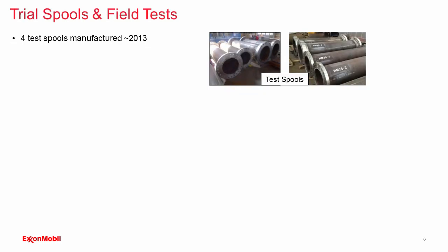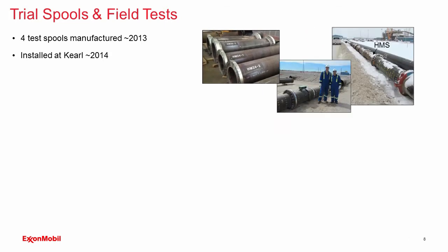We made some trial spools, some trial pipes. These pipes, 4 test spools, were manufactured in 2013. They were about 3 meters long, and they were 24 inches in diameter and 30 inches in diameter. That's 0.6 meter and 0.75 meter in diameter, and they were installed at the Kearl Operation in 2014. You can see there a picture of an ExxonMobil engineer and a POSCO engineer at the Kearl site. And then notice the high manganese steel test spool there. There's a number of flange locations adjacent to the high manganese steel spool. I'll explain that in just a second.